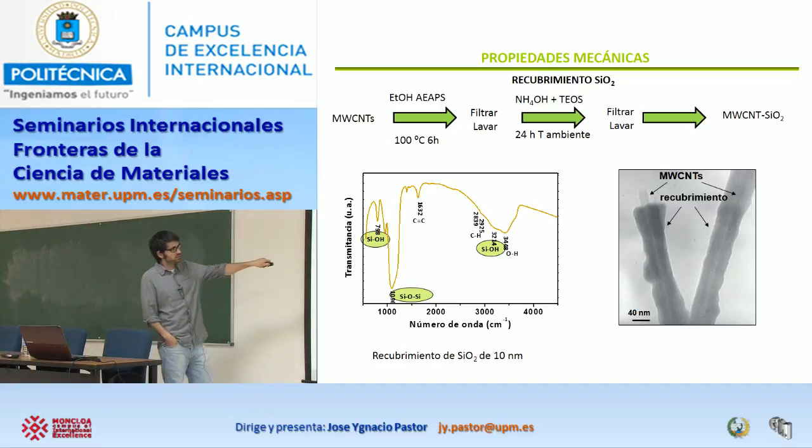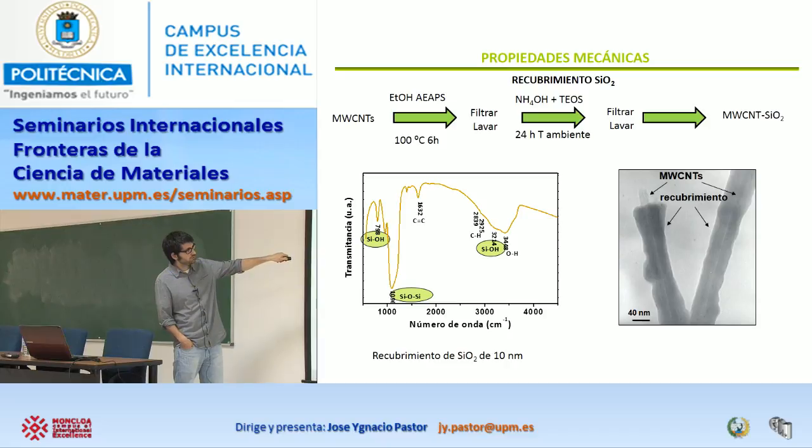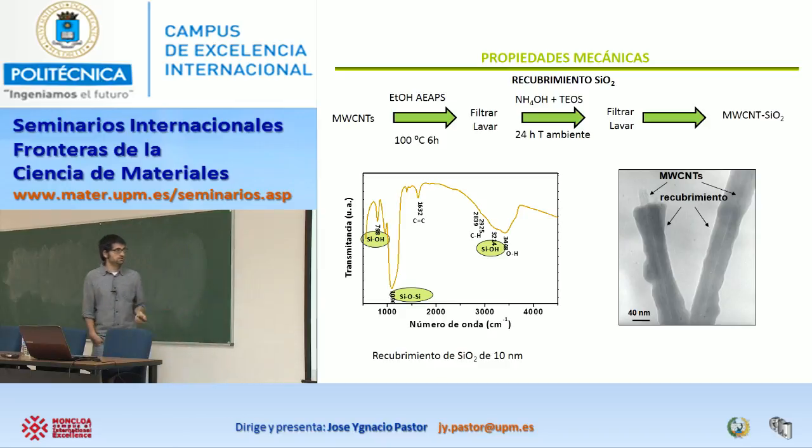Here in a TEM image is our nanotube, and it's totally encapsulated in a perfect shell of silica. In that case, the layer is more continuous, but also thicker. And we characterized that we really have silica and not other elements. Because it's amorphous silica, you cannot see it by X-ray diffraction. The same happens with the boron nitride.